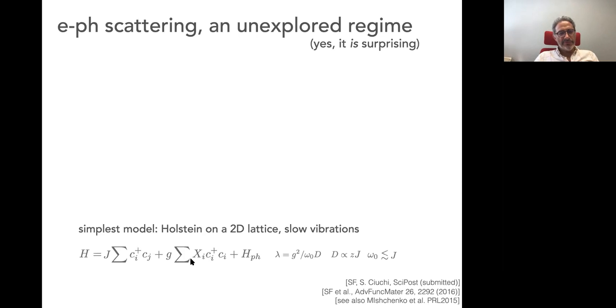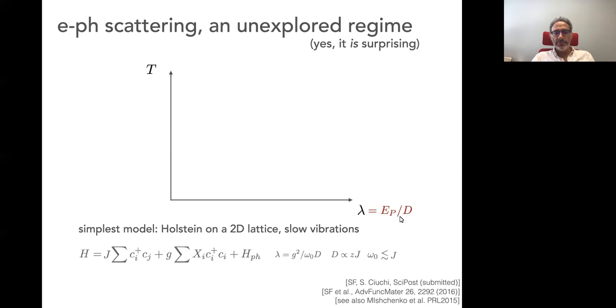All conclusions drawn from here, or almost all of them, also work for other types of interactions, like the Peierls type or non-local interactions that apply to organic semiconductors. The interesting thing here is to show a phase diagram as a function of two parameters. One is temperature, which was really neglected at the beginning. The other is the dimensionless coupling lambda, essentially the ratio between the energy you gain in forming a polaron and the bandwidth.